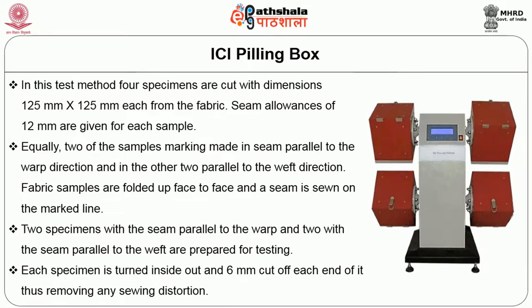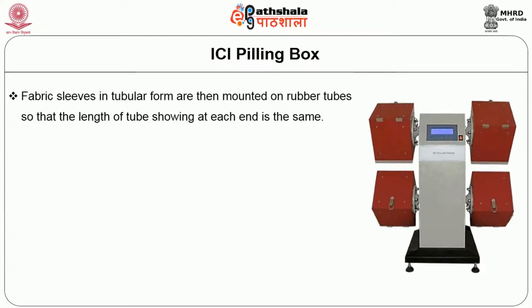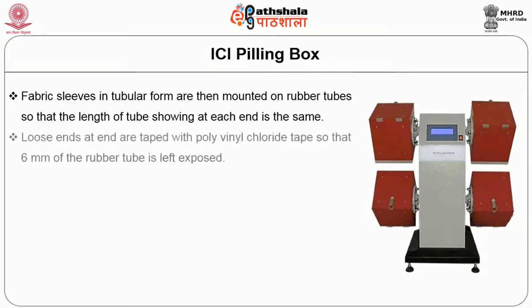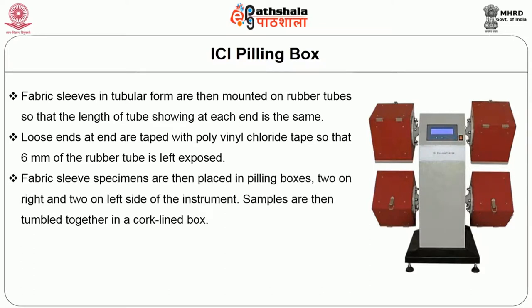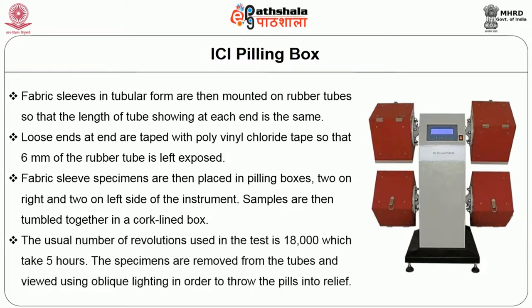Each specimen is turned inside out and 6 mm is cut off each end of it, thus removing any sewing distortion. Fabric sleeves in tubular form are then mounted on rubber tubes so that the length of tube showing at each end is the same. Loose ends are taped with polyvinyl chloride tape so that 6 mm of the rubber tube is left exposed. Fabric sleeve specimens are then placed in the pilling box instrument, 2 on the right and 2 on the left side of the instrument boxes. Samples are then tumbled together in a cork lined box. The usual number of revolutions used in the test is 18,000, which accounts for 5 hours.